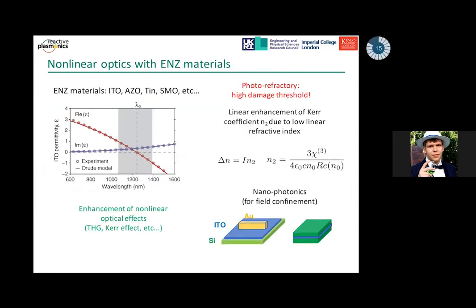Moving to more conventional parametric nonlinear optical processes, a lot of effort in the project was devoted to studies of the so-called epsilon near zero materials, in particular indium tin oxide. In these materials, you can observe a crossing of the real part of the dielectric constant with zero, and you expect to have an enhancement of all nonlinear processes around this point due to the strong local field enhancement in the interface. For example, in the case of self-action of light, this can be directly seen from the expression of the nonlinear induced refractive index.